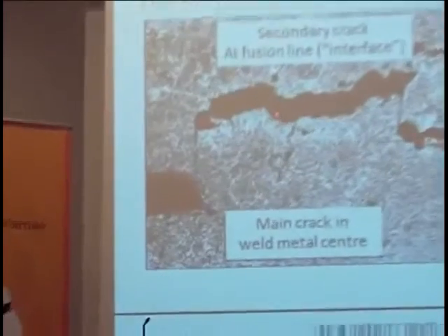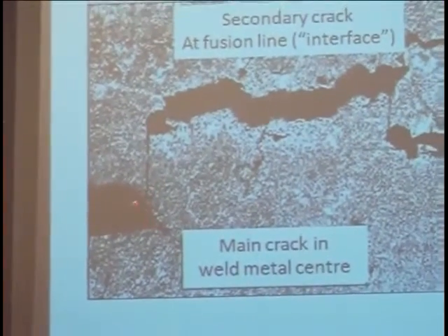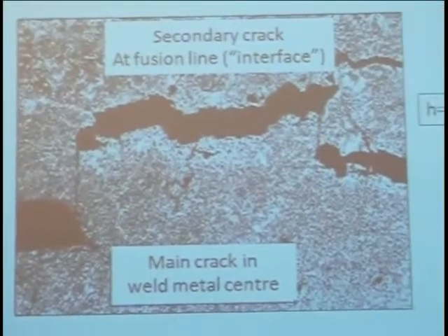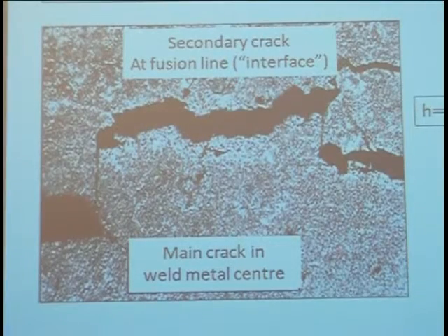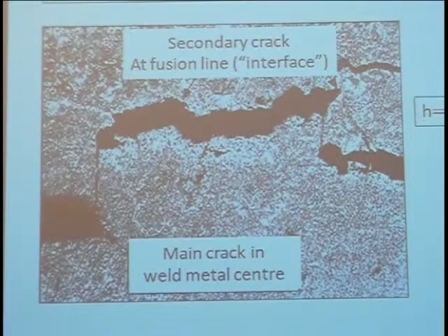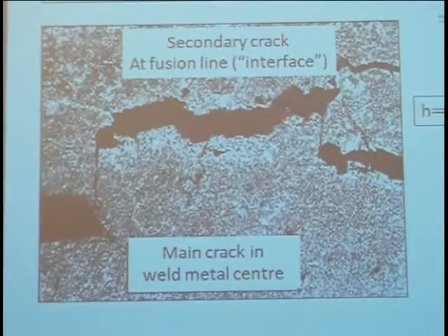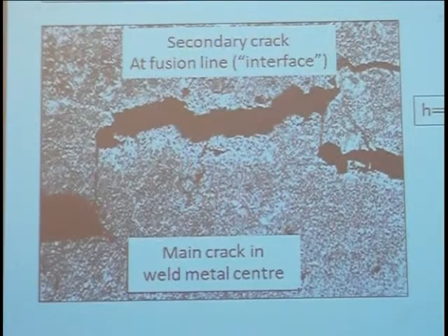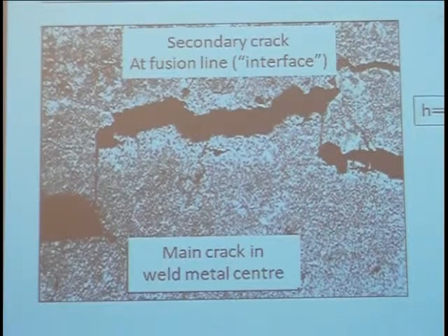And also here, this is another case. Here there was a crack in the center of the weld. And fortunately enough, the crack initiated not at the pre-existing crack, but at the interface, which, had we known nothing about what I was just explaining to you, we wouldn't have understood this kind of behavior. Now we understand at least qualitatively, because here we have high stresses, and it could also have happened here. You see, the crack is here and there, and later this was linked up, and this is the explanation for that.